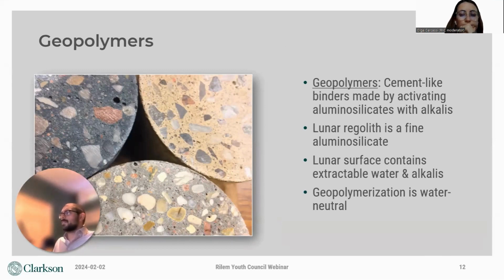Fortunately, over the last several hundred years, concrete researchers have developed a pretty robust toolbox of technologies that can be used to make concrete. One of those technologies is geopolymers, or alkali-activated concrete. Geopolymers are cement-like binders that are made by combining an aluminosilicate material with an alkaline activator. On Earth, we make geopolymers with fly ash or slag cement, but this technology works with just about any aluminosilicate material, of which the lunar regolith happens to be one.